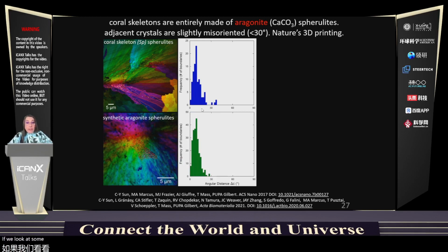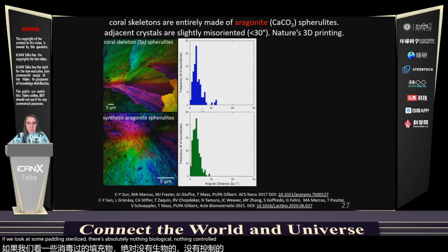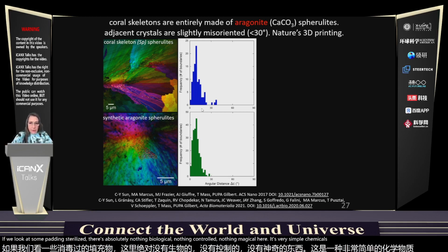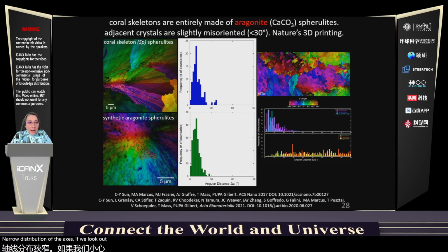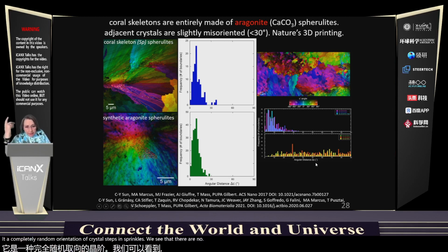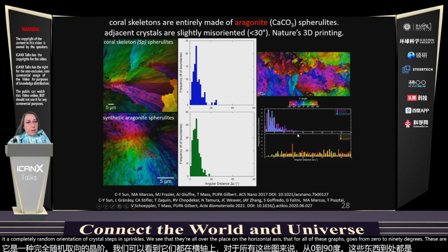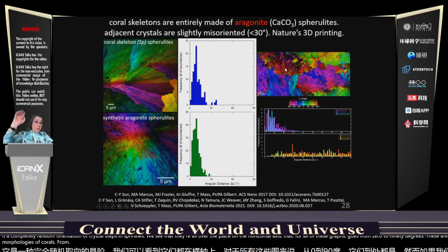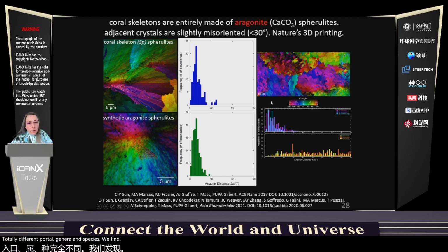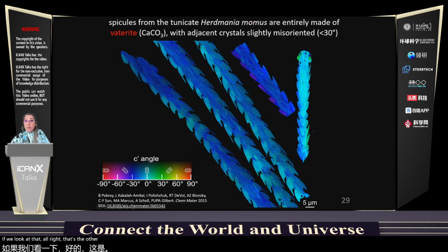If we look at synthetic spherulites, there's absolutely nothing biological, nothing controlled, nothing magical here. It's very simple chemicals added to a solution, and the spherulite grows by itself. We also find a narrow distribution of c-axis angles. If we look instead at a completely random orientation of crystals, like in sprinkles, we see that they're all over the place on the horizontal axis, which for all of these graphs goes from 0 to 90 degrees. Whereas if we compare three completely different morphologies of corals from totally different coral genera and species, we find that all of them have this narrow distribution of angular distances, and all of them below 30-35 degrees. If we look at vaterite, that's the other polymorph of calcium carbonate.